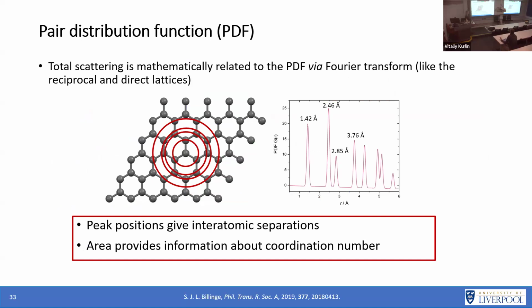But essentially, the pair distribution function is the probability of finding two atoms with a separation distance of r. So this here means that we have a separation between two atoms of 1.42, separation between two atoms of 2.46, etc. This is just a carbon representation for simplicity, but essentially if you had this atom to this atom, this would be our first distance here, etc. So it's a really, really useful technique for looking at materials where you don't have long range order in structure. So definitely have a think about that if you are looking at anything that has disorder in your frameworks. And then again, the peak positions are going to tell you where your interatomic separations are, and then the area is going to tell you something about the coordination number.